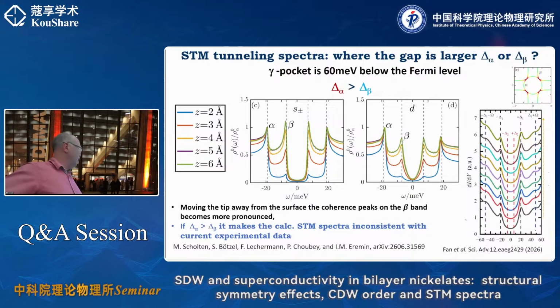I would say that the way to do it is to perform measurements at different tip heights. That would already give you the position of the main gap, whether the main gap is located on the alpha or beta pocket. In addition, it will also change the low temperature behavior. The closer the tip is to the surface, the more you will be picking up the x squared minus y squared orbitals, and the more you will see the V shape. So you need a tip variation, or try to also make the tip not spherically symmetric.